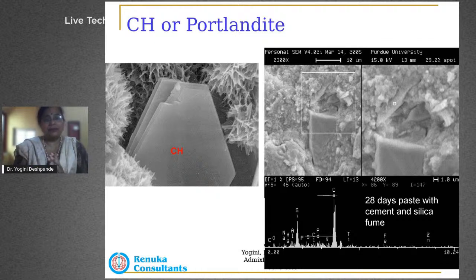This is why we say permeability is reduced considerably when we use an SCM - the presence of CH gets reduced, and any permeability that might remain within the concrete gets reduced, because much of the CH gets converted to CSH, which is a far denser product with very, very few pores left for water, chloride, or any other gaseous ingress.